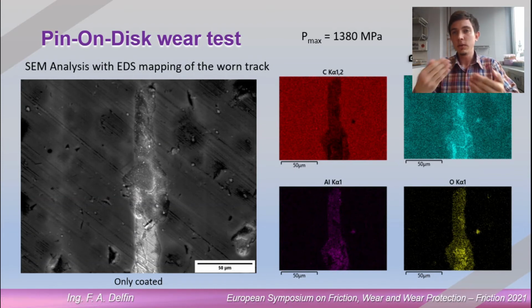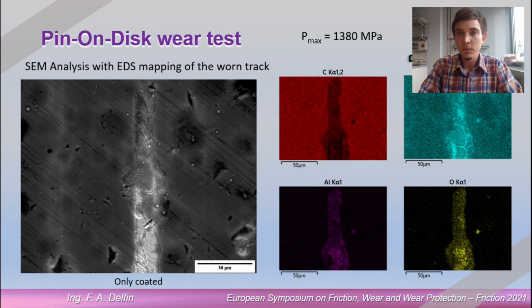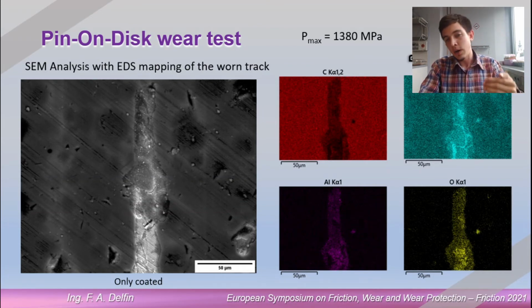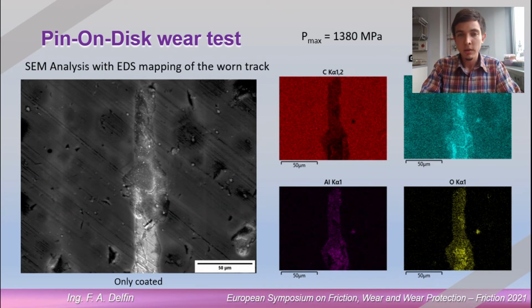When you have the DLC coating and start sliding with any material, you get the transfer layer of the sp2 fraction of the DLC coating, I mean the graphite fraction. So if you form the transfer layer and the third body, you have a dry lubrication system, a solid lubrication system.